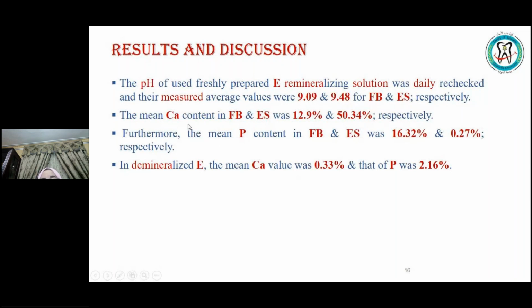The mean calcium content in the fish bone and the eggshell was 12 and 50 respectively, where the calcium content was higher in the eggshell. Furthermore, the mean phosphorus content in the fish bone and the eggshell was 16.32% and 0.27 respectively, where the phosphorus content was higher in the fish bone, much more than the eggshell. In demineralized enamel, the calcium value was 0.33%, and that of the phosphorus was 2.16%.